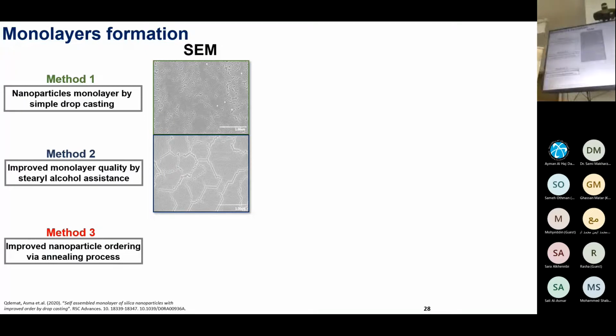In the third method, I attempted to use the heat treatment method, and the idea was to put the monolayer obtained in method 2 in the oven, to melt the stearyl alcohol, which leads to more free particles, and these free particles will lead to more order for further self-assembly. Via further self-assembly, we can solidify the ordered monolayer with only a minor change of the volume, which is actually the advantage behind not using